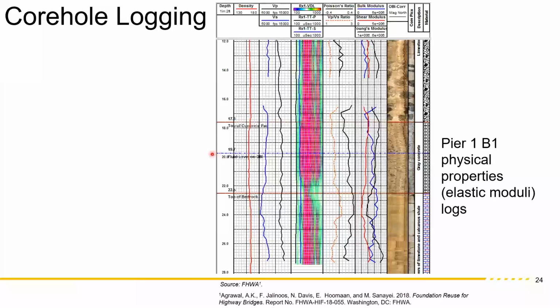Here we have a sonic tool. Basically, we have a sonic source, which is a single impulsive source, not a resonant pulse source, and a number of receivers in line down the borehole. So we're looking at the time difference as the wave travels up the core hole, so as to get the velocities in place. So we get a full waveform, just similar to that cross-hole sonic, but it's not a resonant signal. So we can pick the compressional wave and shear wave, and so we can pick the compressional wave velocity and shear wave velocity.